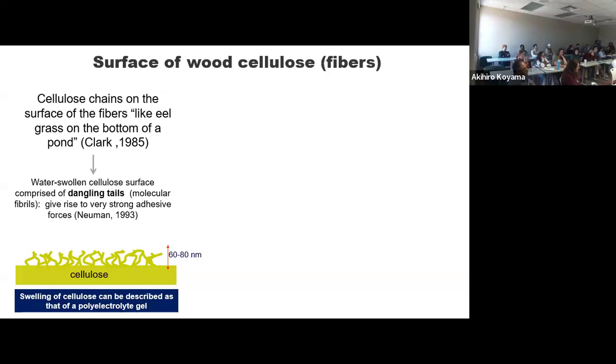So in the presence of water, the surface of the fibers will look like this. It's not something that is just flat. There is something. And these are highly hydrated chains of cellulose, not a single molecule of cellulose, but chains of cellulose forming fibrils that feel like a polyelectrolyte, like a polymer that is charged, highly hydrated, and is coming out from the surface. Beautiful, because that also explains the adhesion between fibers in the paper-making process. So these materials have to be active in that process.